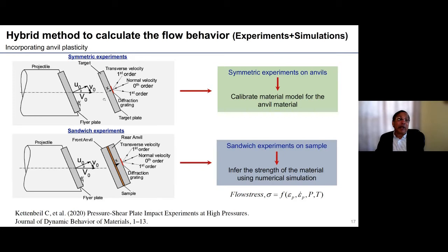We have developed a technique whereby we characterize the anvils. We know that the anvil plates are going to undergo inelastic deformation, so first we calibrate the anvils. We calibrate the anvils by performing impact experiments using oblique impact at nominally the same velocities as we would use in our pressure shear plate impact experiments on the sample. We conduct this at similar velocities and similar pressures so that we can calibrate a material model. What do we mean by calibrating a material model? I'm going to show you some of the details later, but essentially we are developing the flow stress as a function of strain rate, temperature and so on for these anvils by performing independent measurements. So first we calibrate the anvil material, and now the anvil material is completely characterized.